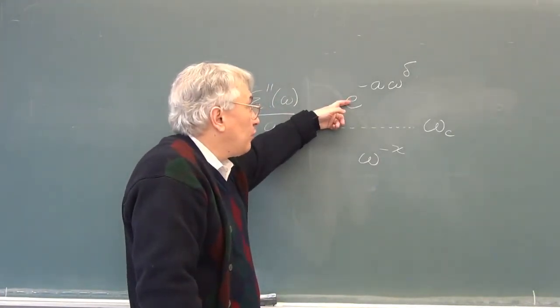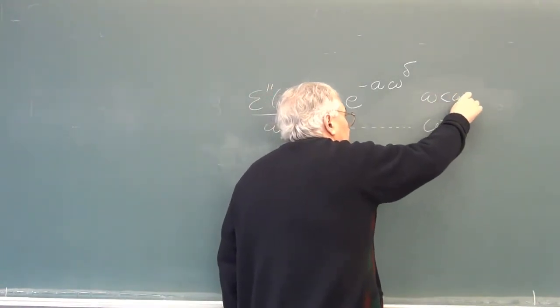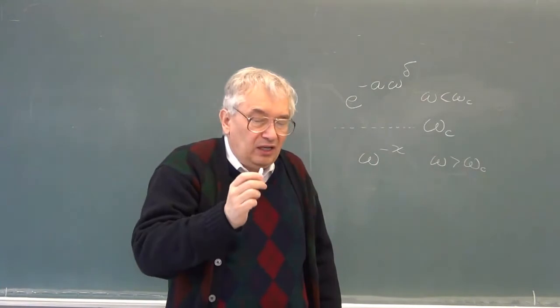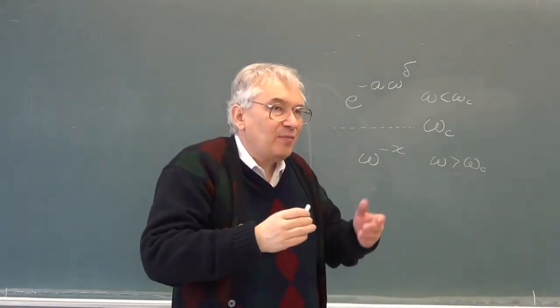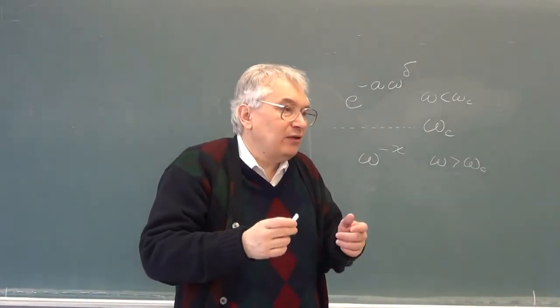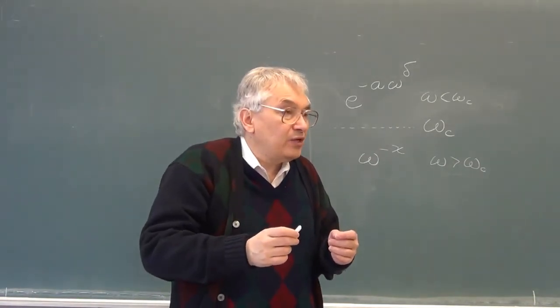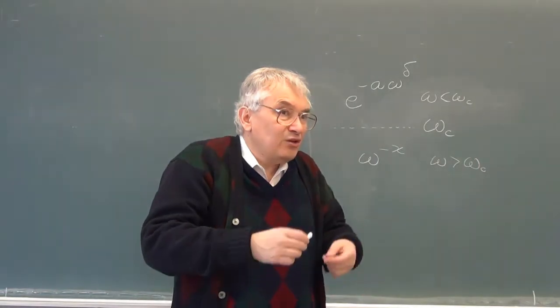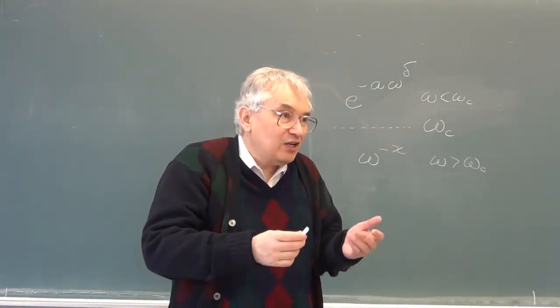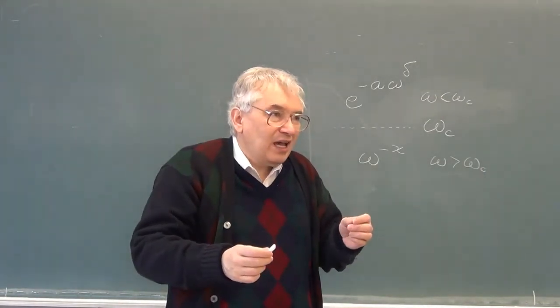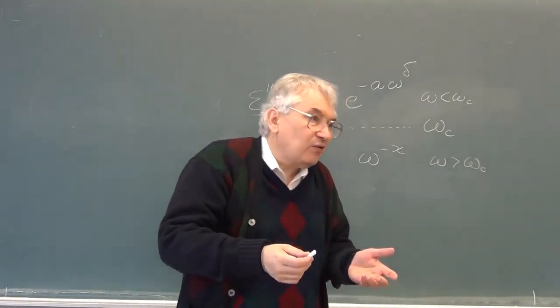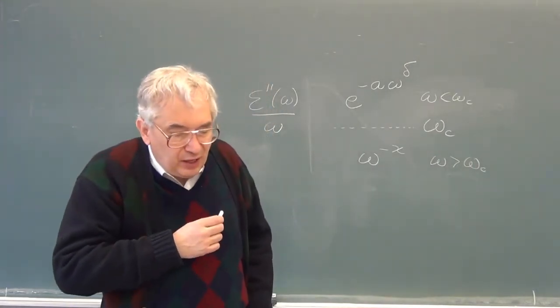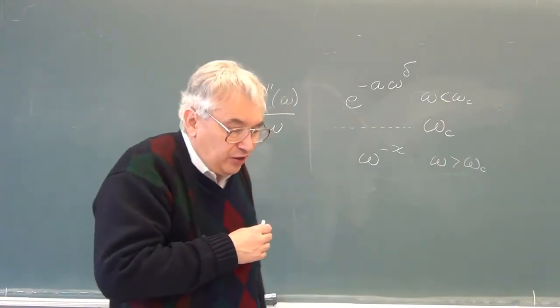Nonetheless, we have this function. By direct analogy with the discussion of viscoelastic response, this function has two forms: e to the minus a times omega to the delta, and omega to the minus x. These two functions are separated by some crossover frequency omega_c. So you have one behavior at low frequencies and another behavior at high frequencies. The polymer chain is a big complicated object, and it can have several physically entirely different ways of changing which way its end-to-end vector points.